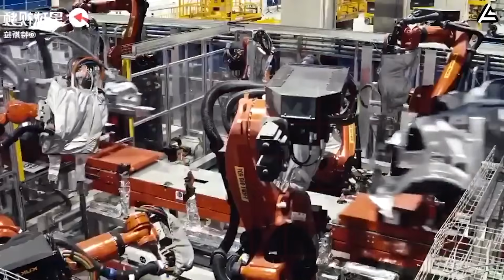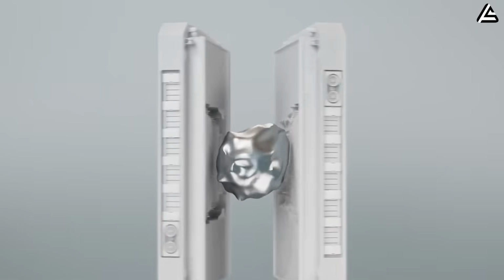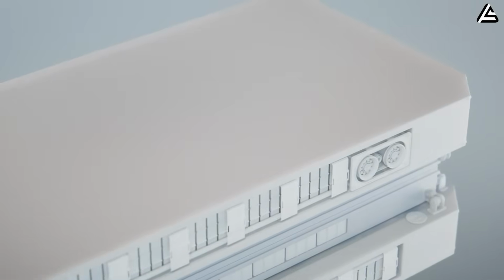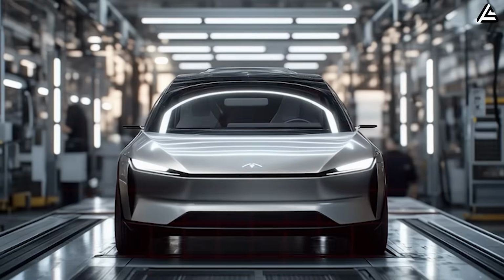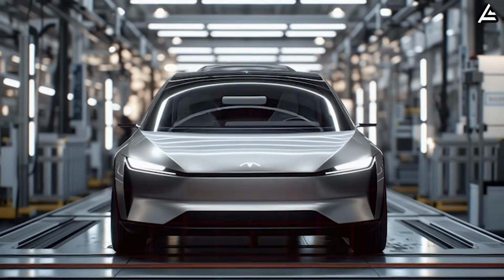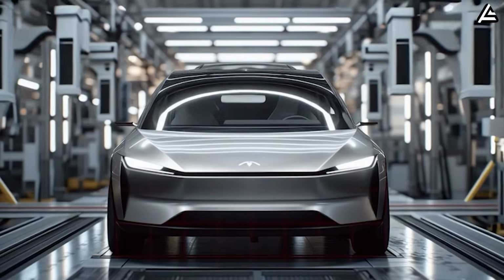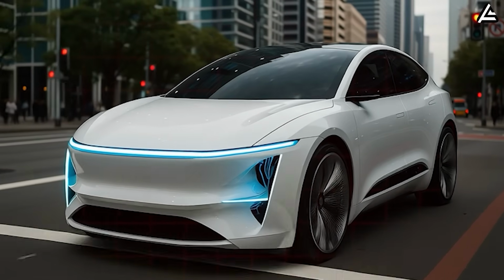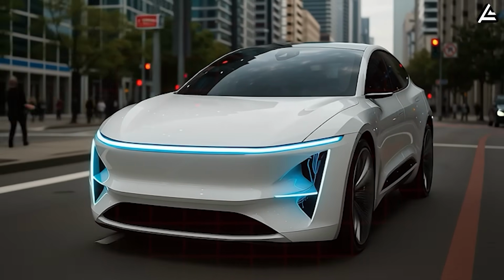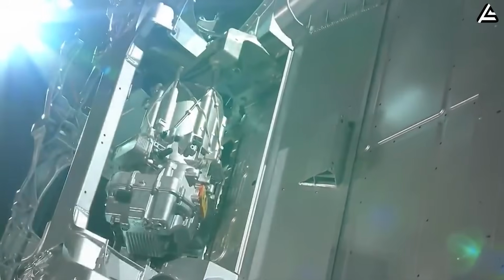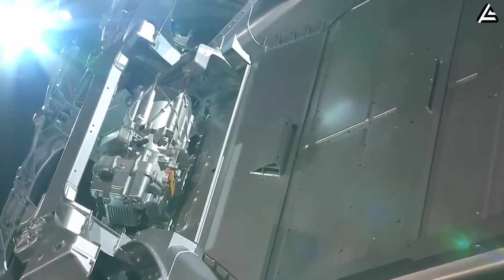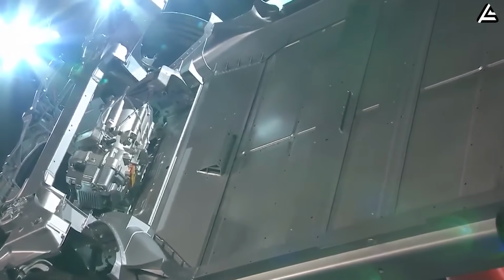Another advantage comes from weight savings. By eliminating dozens of steel brackets, reinforcements, and weld plates, Tesla is expected to remove 120 to 180 pounds from the rear structure alone. In a compact EV where efficiency is everything, that could translate to an additional 12 to 20 miles of range, or allow Tesla to shrink the battery pack while maintaining the same 240 to 270 mile target range. Either outcome drastically reduces cost.